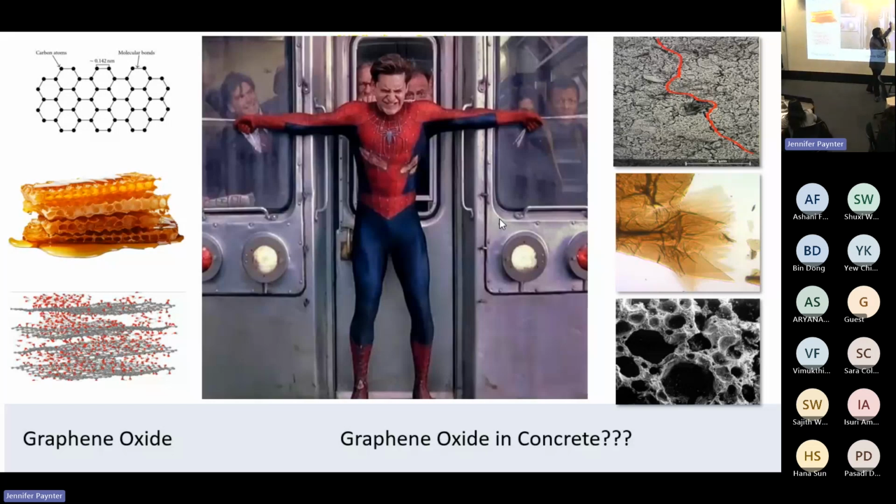On this side, you can see the findings from our work. On the top, you can see how the crack path avoids wherever the graphene sheets are. This is a very new finding. We still have not published it yet. And the second one, I couldn't resist putting it here. You can see the graphene oxide sheet opened up like a stack of cards. These thin sheets are the graphene sheets. All together, we call it graphene oxide.